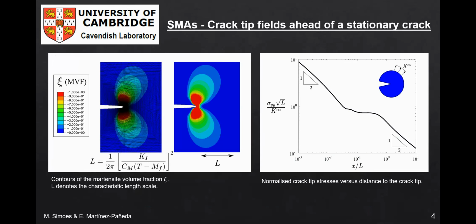So from a fracture mechanics perspective, what is more interesting is that the high stresses that are present at the crack tip will trigger a stress-induced phase transformation. And as a consequence, there will be a small region at the crack tip where the material is in its martensitic phase. In the slide, you can see a calculation of a stationary crack, so no phase field.